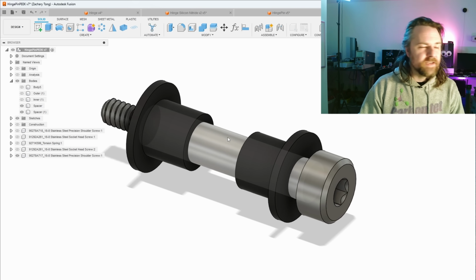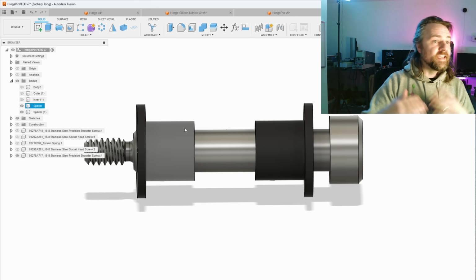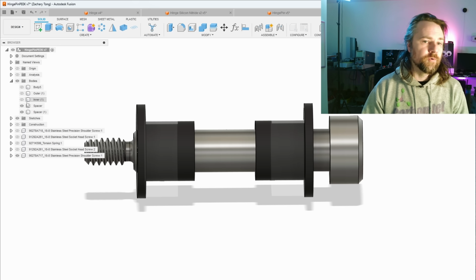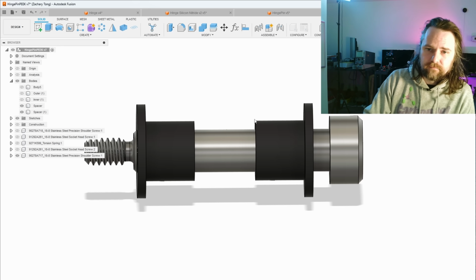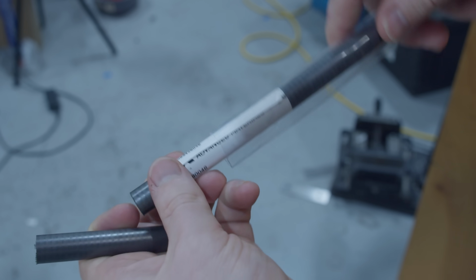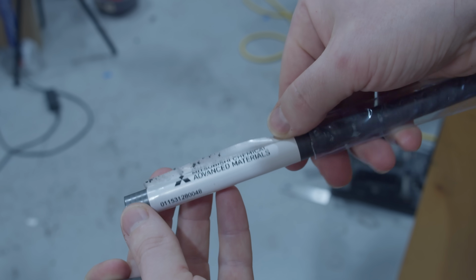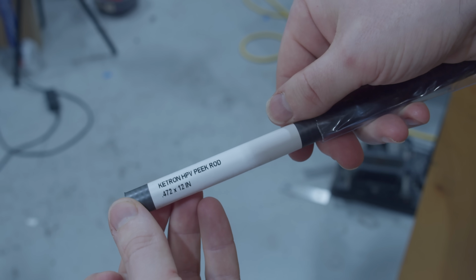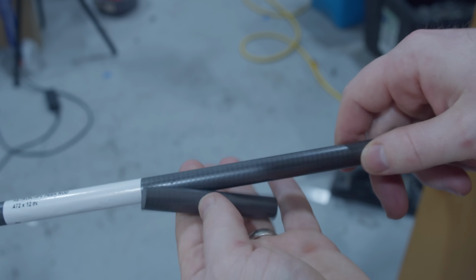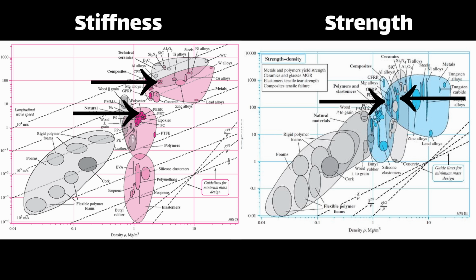So here's what the little spacers or bushings look like, and those provide the interface between the hinge and the shoulder bolt. And this solves a couple problems for us. These bushings are made out of a Teflon and graphite-filled PEEK material. This is an engineering polymer that's rated for space, so it has very low outgassing characteristics. It handles extreme temperatures very well, from low to high temperatures. It doesn't get too brittle. It's not quite as strong or stiff as aluminum, but it's pretty close for a polymer. And then this particular variety has both Teflon and graphite in it, which means it's naturally kind of slippery. It's a low friction material. Also, it's just kind of weird, like when you hit it against itself, it sounds...